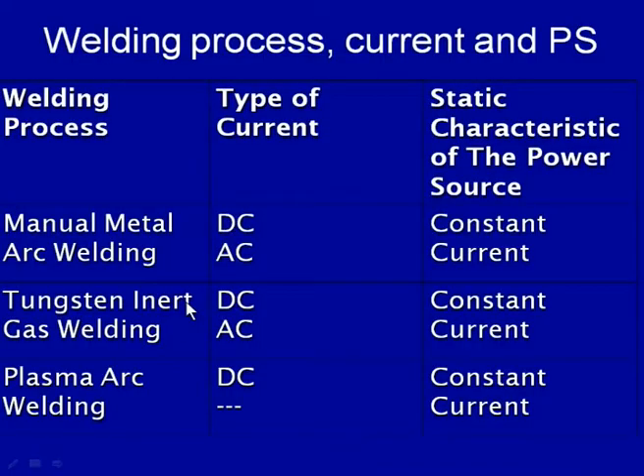Similarly, in tungsten inert gas welding process, we can work with both AC and DC depending upon the requirement, and again the constant current type of the power source is used, because the tungsten inert gas welding process is generally controlled using the manual control, and there is always possibility of having the fluctuation in arc length. So, to maintain the arc length, therefore, the constant current type of the power sources is used, so that the uniform heat can be generated, but it can work with the AC or DC depending upon the kind of heat control or the cleaning action is required or the stability of the arc is required.